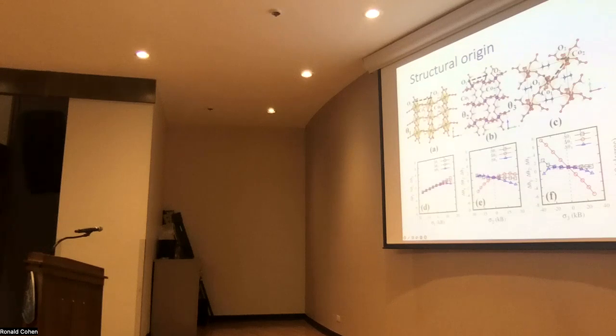So we further took a look at the structural origin of that effect, and it turns out that if we compress the material along the C direction, there will be a huge change in the polyhedral angle right here, the one that I give with the red symbols. What happens if I compress along the C direction is that there will be oxygen octahedral tilts, and those tilts will deform your framework, and that is what will make the contribution to the sign of the piezoelectric coefficient in the case of the longitudinal response. On the other hand, for the transverse response, we actually found that it's the tilt of the molecules that is responsible for the sign and for the response of the material to the applied stress.